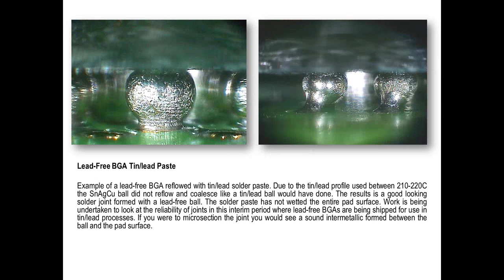But these are examples of what we did see during the transition where BGA manufacturers converted to lead-free, but in some instances didn't tell us. So we were using tin-lead technology, and you got joints looking similar to this. One on the left-hand side, which hasn't collapsed. So the lead-free ball has not got to a complete reflow temperature. We've formed a joint, which possibly is completely reliable, but it just doesn't look right. And then on the right-hand side, the balls have not become liquid. The solder paste has reflowed, wet to it. There's been a slight misalignment on the pad surface, but we've made joints. Again, most quality engineers wouldn't accept it, but it'd be interesting to actually see if you put that through temperature cycling, how long it actually lasts.